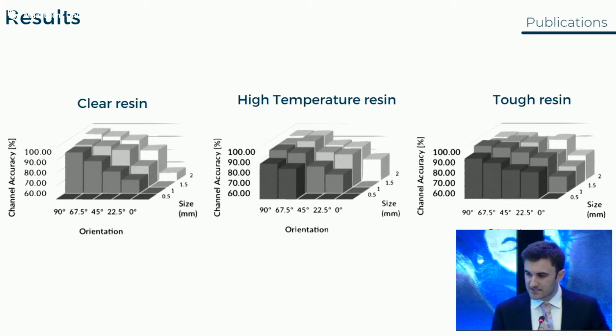If we look at the results for the printing of closed channels, we can see that the clear resin slightly underperformed with respect to the tough resin and the high temperature resin, but nonetheless we were able to achieve channel sizes of about 0.5 millimeter, so 500 micrometers.